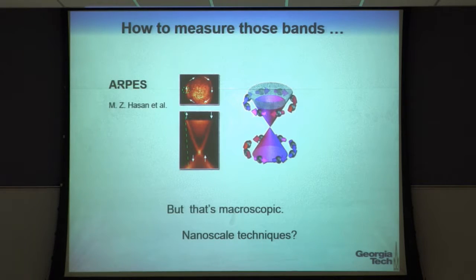Well, the standard way to measure electronic band structure is angle-resolved photoemission spectroscopy, ARPES. Okay? And these bands that you see, this is energy as a function of a slice through k-space, through momentum space, that shows the Dirac cone for a particular topological insulator material. And if you measure around here, what you see, this was spin-resolved photoelectron emission, you find that the spin direction also changes around that cone.